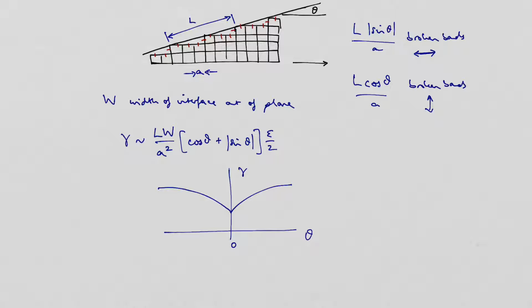Okay, the cusp is reduced a little bit by entropy effects. There's also entropy here, obviously. We're creating some steps here in the surface, and potentially atoms can now diffuse, and those are quite happy places for a little atom to go and join onto. So at finite temperature there's some entropy associated with these.